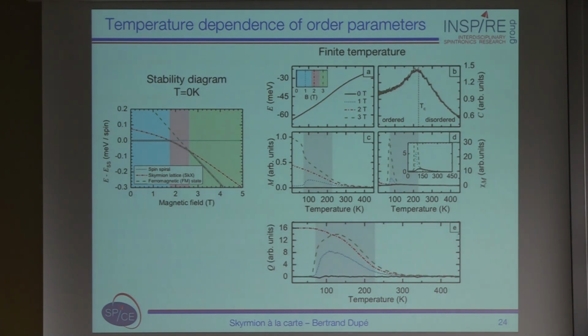Now, for different magnetic fields, we always started with the ground state, and we did parallel tempering Monte Carlo. Here is an example. I show you only 4 curves for 4 different magnetic fields, depending on the ground state: 0 Tesla, 1 Tesla, 2 Tesla, 3 Tesla. You have 2 curves starting from the spin spiral ground state, 1 from the skyrmion lattice ground state, and 1 for the ferromagnetic ground state. And I plot the different order parameters that we first look at, namely the energy, the magnetization, and the topological charge. You see that in the energy, all the curves are on top of each other.